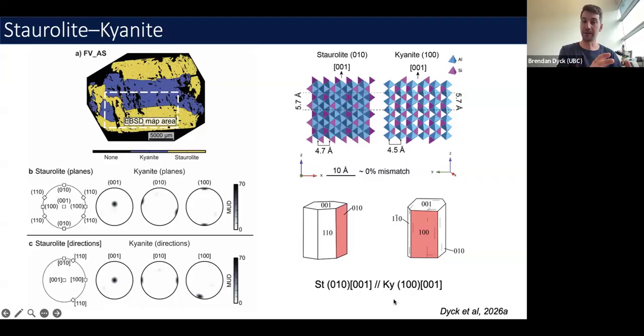Once we have that relationship, we can then visualize what the grain boundary, or what the interaction of these grain boundaries might look like, using a program like CrystalMaker, or there's a few different crystal visualization programs that work very well with this. So we take the crystals, staurolite and kyanite, we cut them along these planes that we're observing are parallel with each other in the EBSD data, and then we orient those planes so that the directions that are parallel with each other remain parallel. And we do that with staurolite and kyanite.